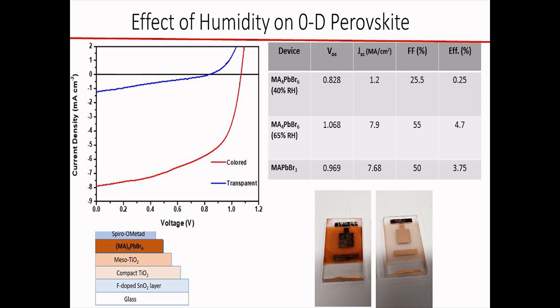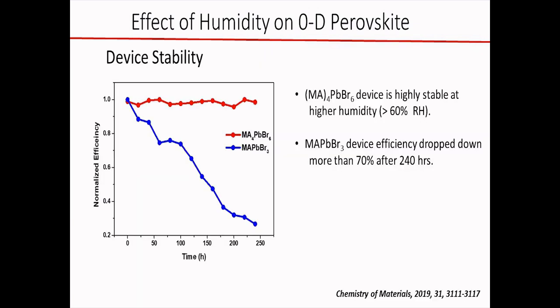At low humid conditions, the device doesn't work. It only results in 0.25% efficiencies, whereas under the high humid conditions, we end up getting around 5% efficiencies. So we studied the stability of these devices at 60% RH.